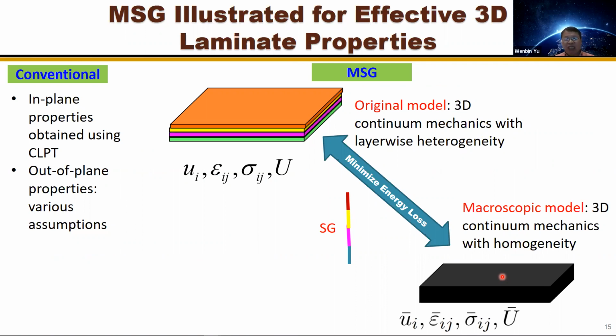We treat a stack of laminates as a homogeneous material, kind of like a black aluminum. Then the conventional approach: they use the classical lamination theory to get the A matrix, then get your in-plane properties. For the out-of-plane properties, they make various assumptions through the thickness, then calculate the transverse Young's modulus, Poisson's ratio, CTEs.